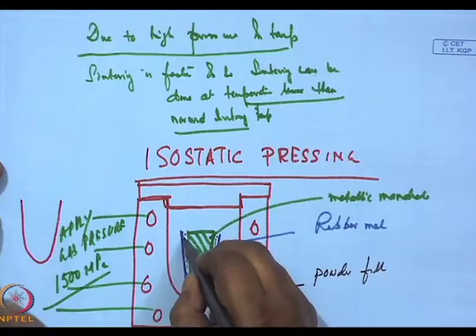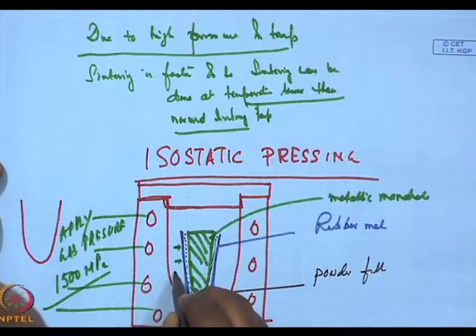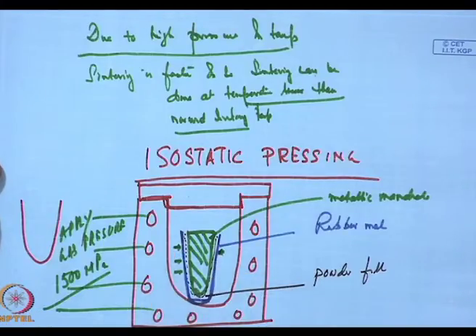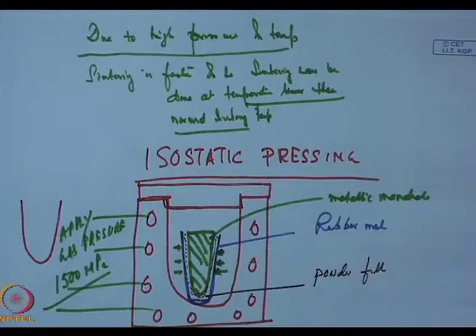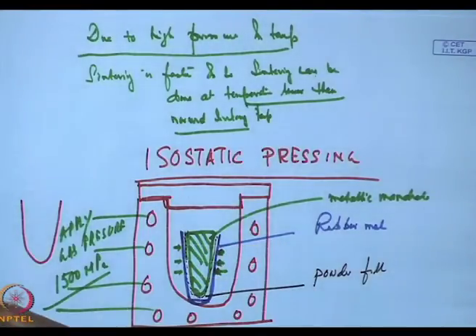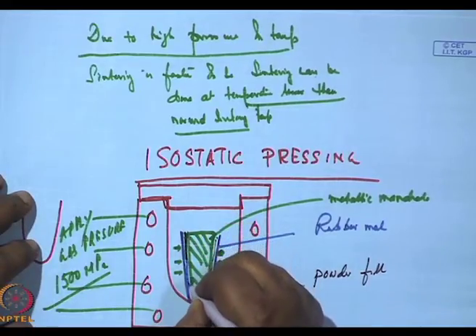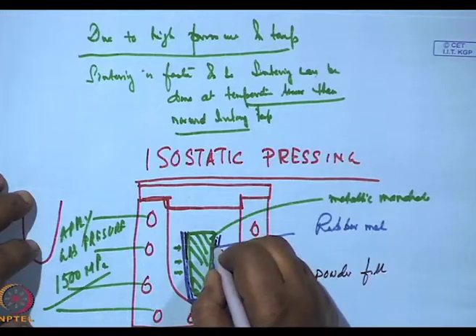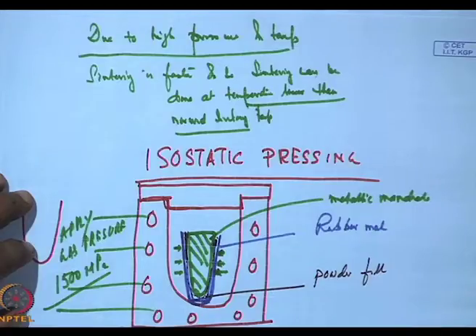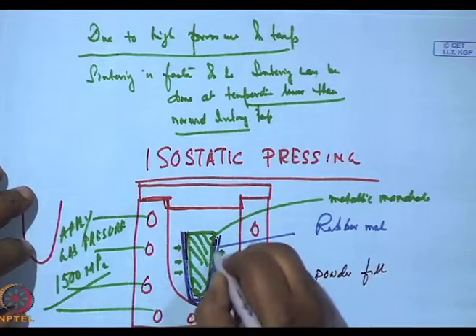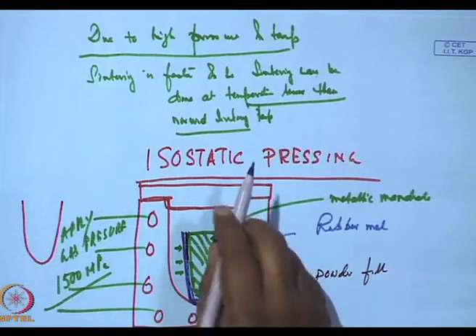What will happen? This rubber mold under pressure would have squeezed much more, which manually is not possible. Further, this pressure acts in all directions. So this is better than uniaxial pressing, where we had pressure only from two directions, but here we have got pressure from three different directions. And hence, after the pressure is allowed to drop, these powders would get compacted very uniformly, and I would get almost 99% compaction.